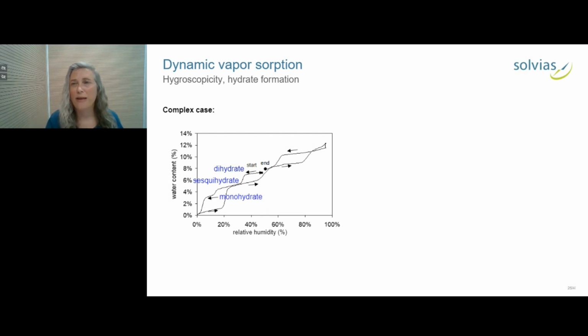And as we lowered it further, it converted into a monohydrate. As we lowered it further, we got an anhydrous form. Then as we raised the humidity, we see that it bypassed the monohydrate and converted directly back into the sesquihydrate, then at higher humidities into the dihydrate, then at even higher humidities, we found a trihydrate of this form. And finally, at the end, going back to 50% relative humidity, we're back at the dihydrate. And you'll see there's a hysteresis in these transformations, and this is a kinetic effect because basically, except at a transition point, thermodynamically only one of the forms would be stable.